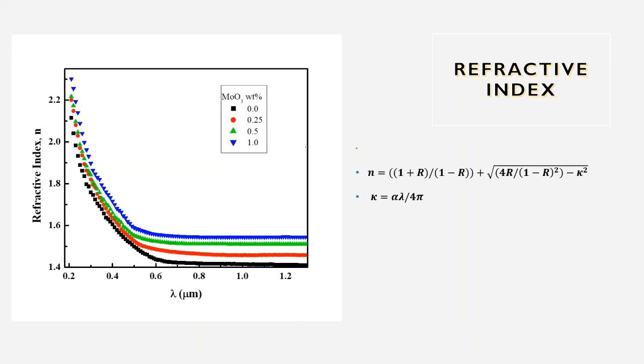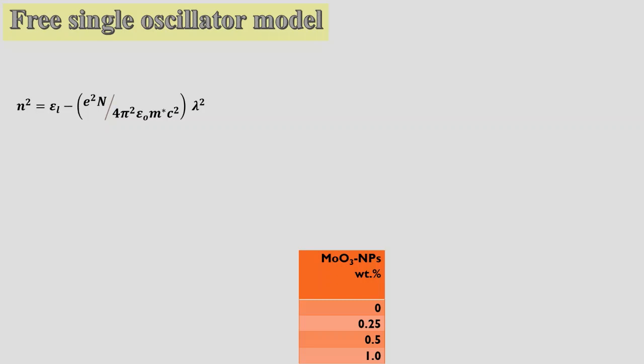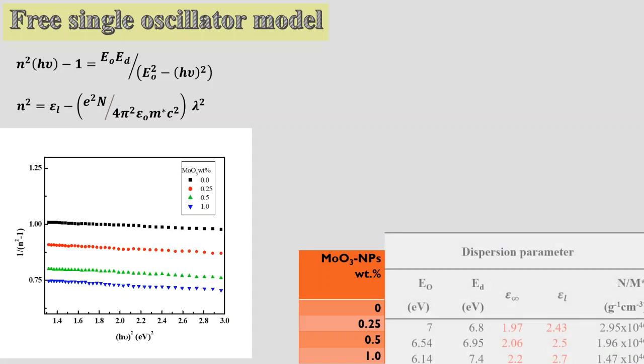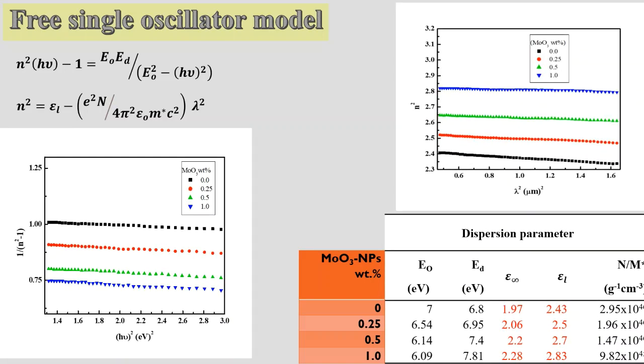From this equation, we calculate the refractive index and draw it as a function of wavelength. And we observed that the refractive index increases with increasing the concentration of metal oxide. We use the single oscillator model in order to calculate the oscillation energy, dispersion energy, infinite dielectric constant, and lattice dielectric constant, and free carrier concentration.